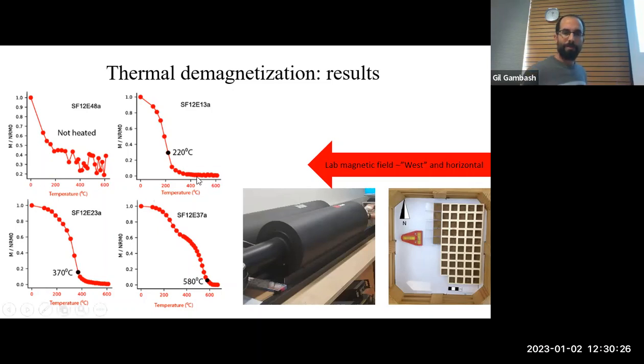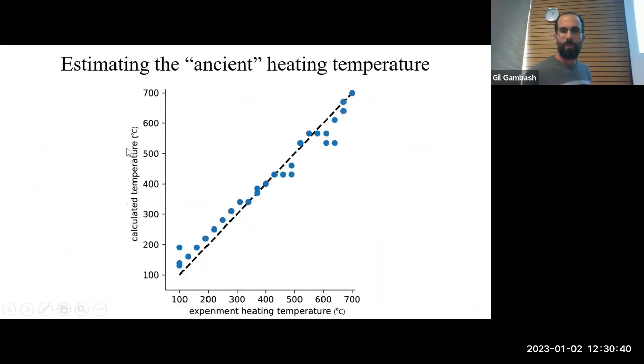But this hasn't been done, at least not for these low temperatures. So this way we reconstructed the temperature at which it was heated. Now we reconstructed the ancient temperature, but it's not really ancient because this is experimental archaeology. We heated it in the lab. So you can see the results here. This is the experiment heating temperature, what we did in the lab. And this is the calculated temperature. And you can see a very good correlation here.